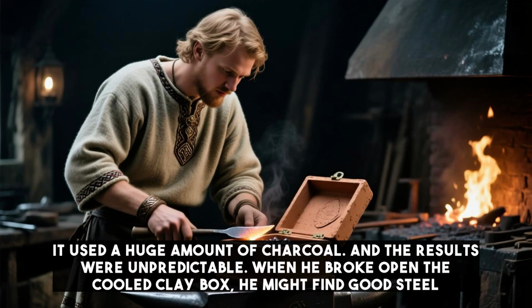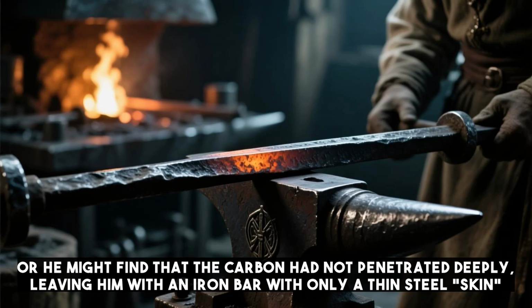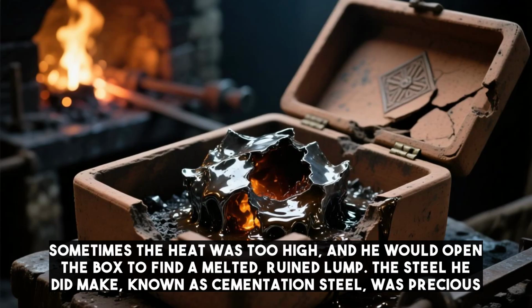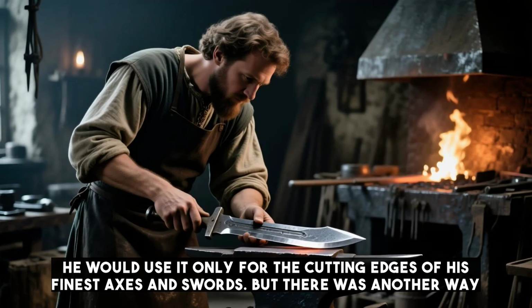When he broke open the cooled clay box, he might find good steel. Or he might find that the carbon had not penetrated deeply, leaving him with an iron bar with only a thin steel skin. Sometimes the heat was too high, and he would open the box to find a melted, ruined lump. The steel he did make, known as cementation steel, was precious. He would use it only for the cutting edges of his finest axes and swords, but there was another way.